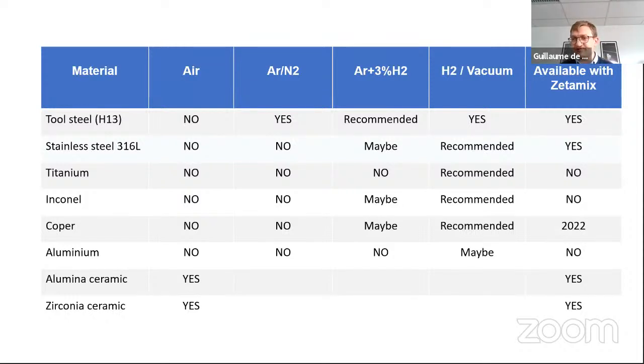The reason we do like a lot tool steel is because it's a lot easier to sinter. It can be sintered at the neutral gas, or even ideally neutral gas with a little bit of hydrogen, which will make it more reliable. Whereas all of the other metals that are listed here would rather be recommended for hydrogen. So you can sinter a few of them under a mix of argon and hydrogen, but it's the ideal conditions where you would get the best densities is pure hydrogen. Of course, you also have ceramics where you don't need any neutral gas. That's something different. They're listed here, but they're no metals, so that's a bit different.